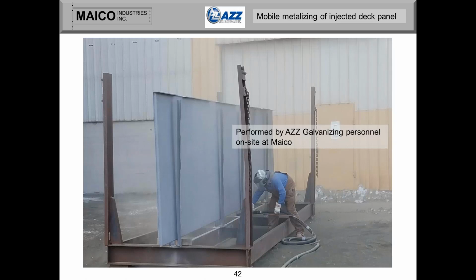This slide here is the mobile metallizing of the injected deck panel. Once the deck panels are injected, we removed them and transported them outside, and AZZ had some personnel on site to do the metallizing at our facility, and these guys were really professionals and did a great job. They initially had to surface blast the material prior to metallizing, which is an alternative to hot dip galvanizing. Since this panel could not be submerged in molten zinc after the polyurethane core was injected, in order to receive the cathodic protection, the next best thing was metallizing. So they came to our shop and performed that function.